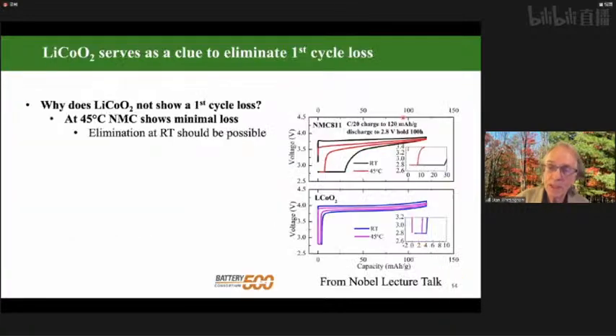And there are clues that we can solve this problem, because if we look at pure lithium cobalt oxide, very similar structure, it does not show a first cycle loss. So we look at the 80% nickel material, black is room temperature, red is 45, and you can see in this case we just charged it at 120. On discharge at room temperature, we now held it for 100 hours, and you can see we got all the lithium back in. So again, clearly diffusion controlled in some manner. Lithium cobalt oxide is the same at room temperature and 45 degrees centigrade. The only difference really between these, this is a single phase reaction, and the lithium cobalt oxide is a 2-phase reaction. So it's almost exactly the opposite. We'd expect problems with lithium in a 2-phase reaction, not the single phase. So our goal has been trying to make our NMCs behave more like lithium cobalt oxide.